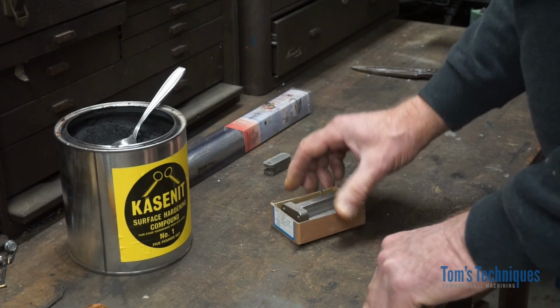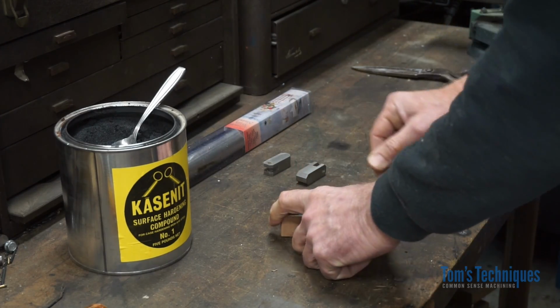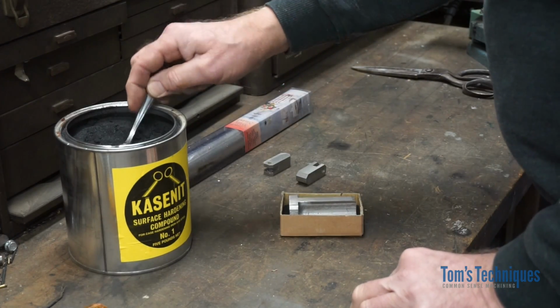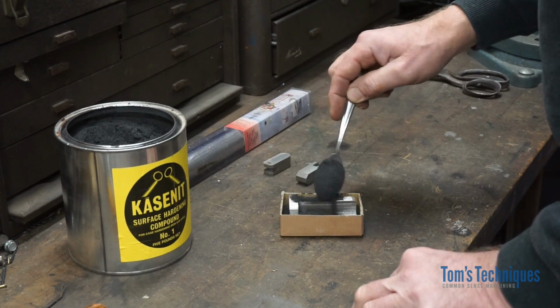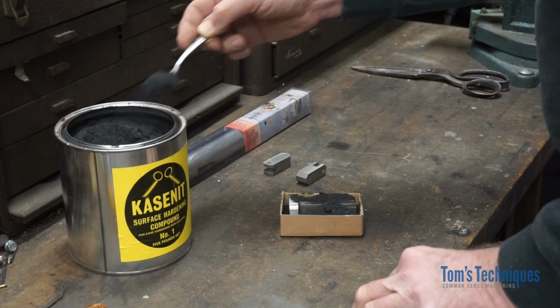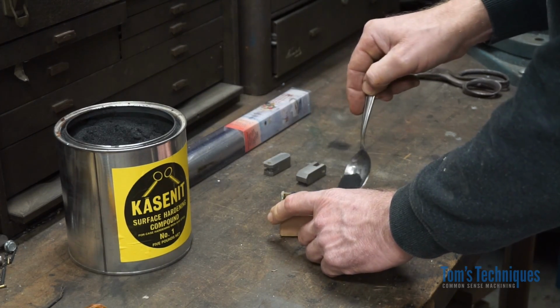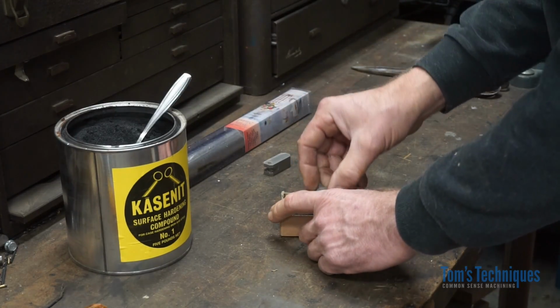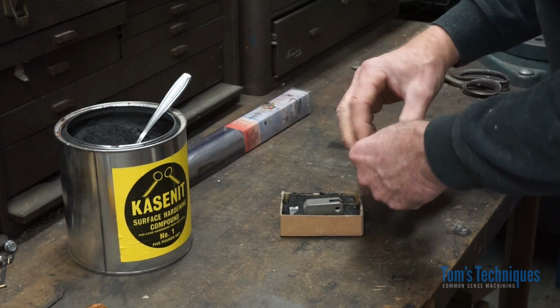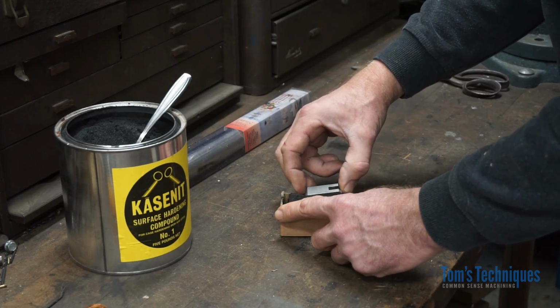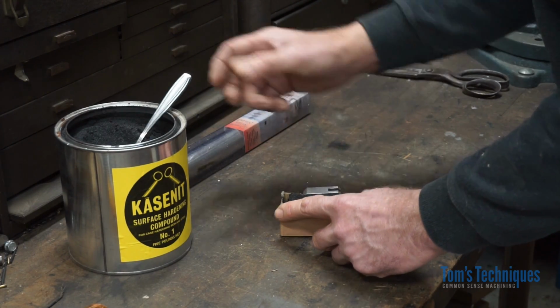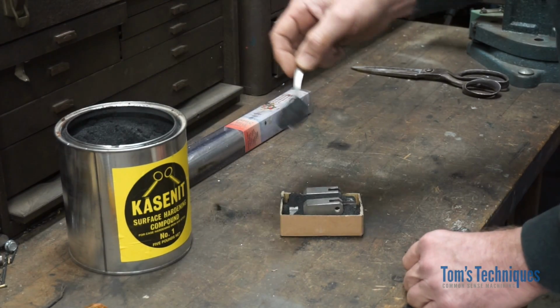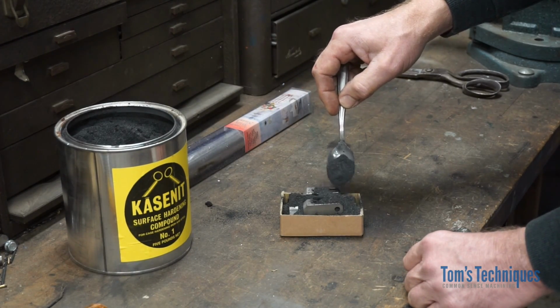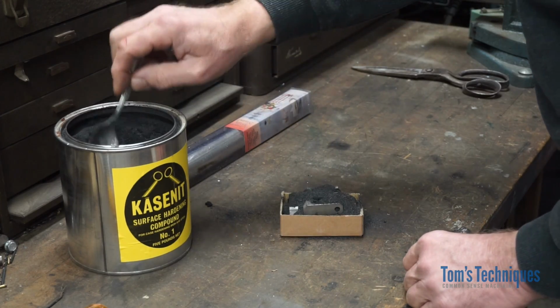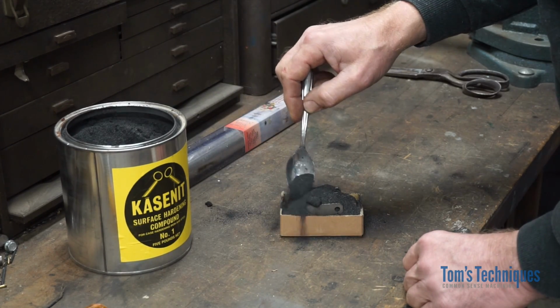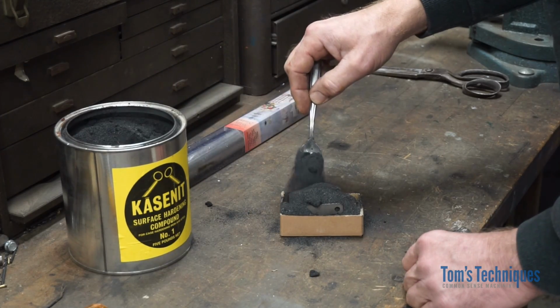So I happen to have this nifty box here all ready to go. We'll just put the parts in there. Add the carburizing compound. Make sure you get all the areas coated. With these parts it's especially important that you get carburizing compound down in the gap here, because this is a functional hardness. We want it to be hard so it doesn't wear against the rotating knurl. So just make sure everything's nicely coated.